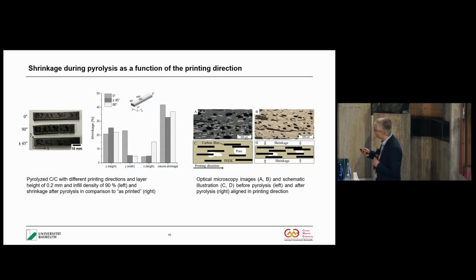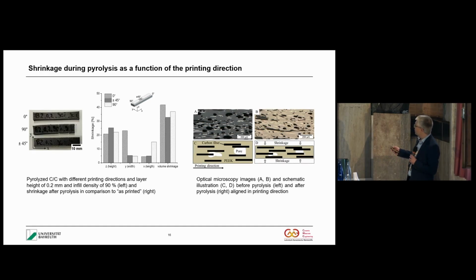Here you can see the samples after pyrolysis, 90 degrees and 0 degrees, where you see, for example, deformation or cracking. But with plus minus 45 degree printing, the shape is quite homogeneous, and you have quite uniform shrinkage, which is important because the carbon fibers impair the shrinkage. Perpendicular to the fibers, you have quite large shrinkage, but in fiber direction, the shrinkage is negligible. That's the reason for plus minus 45 degrees, so that you have more or less uniform shrinkage in every direction.